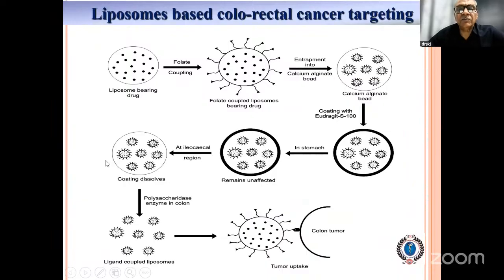This is a schematic diagram of how it will act. These are the liposomes bearing the anti-cancer drug, and the surface of the liposomes is coupled with folic acid. These surface modified folic acid coupled liposomes bearing anti-cancer drug are entrapped in calcium alginate beads, and these beads are further coated with Eudragit S100. This whole system will pass through the stomach and the small intestine. In the distal part of the small intestine, at the ileocecal region, the Eudragit coating is dissolved. Then the calcium alginate beads enter into the colon, where the polysaccharidase enzymes will degrade the calcium alginate beads.